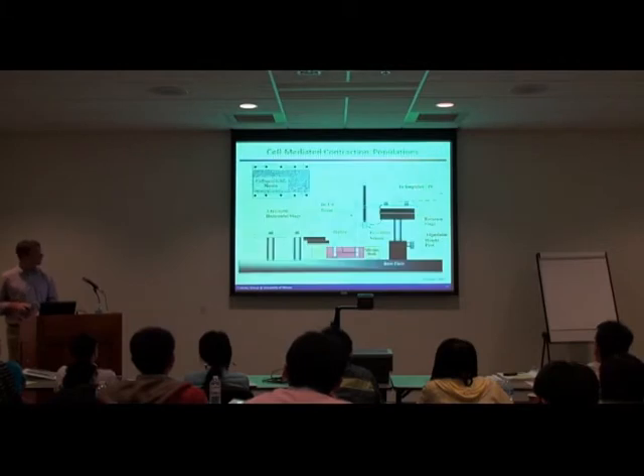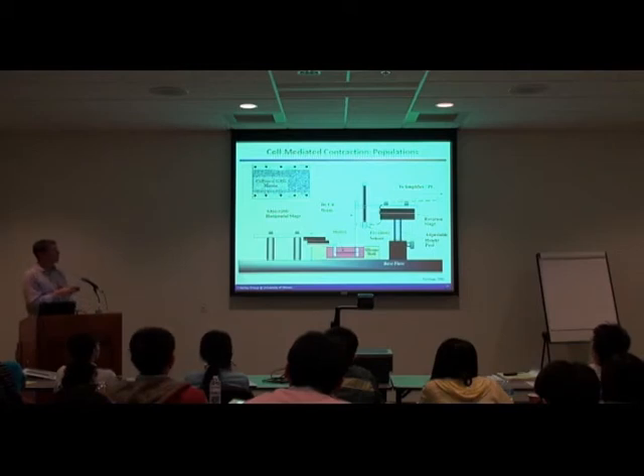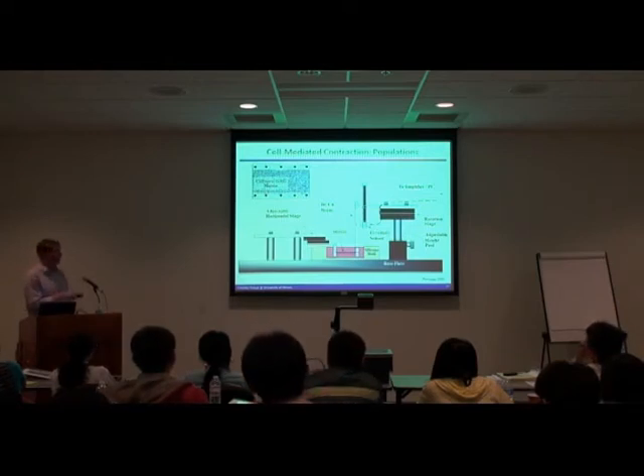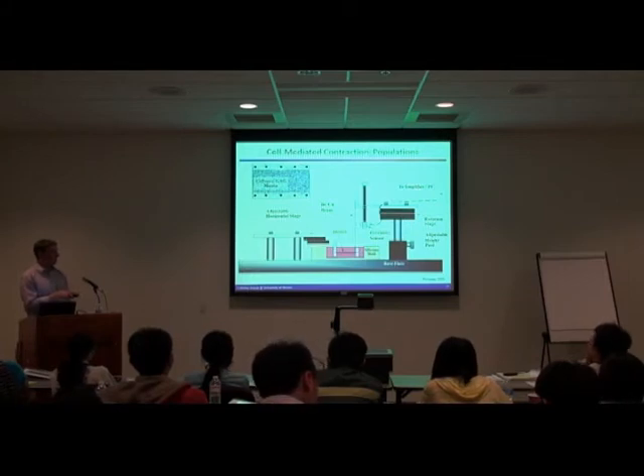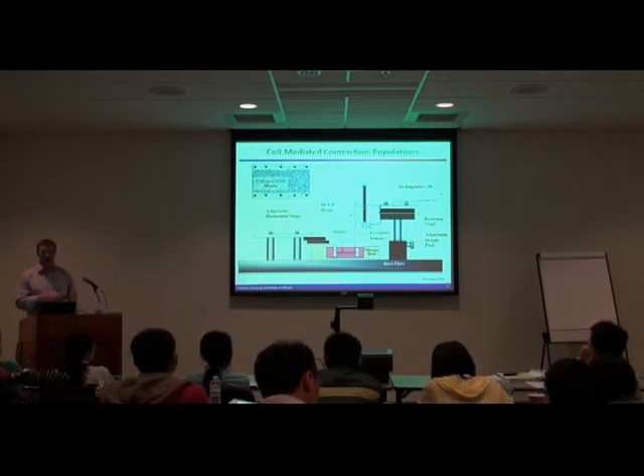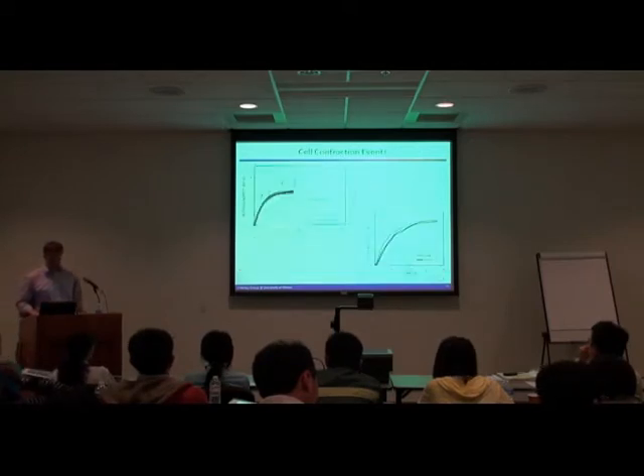And so what this allows us to do is that, well, we can make 2 different types of measurements. And so the first measurement we've been comparing it to was this sort of cell-mediated contraction of populations. And again, this idea is we take our scaffold, we seed it with 1 million or 2 million or 10 million cells, put it into some sort of measuring device. In this case, a colleague of mine, Toby Fryman, built the cell force monitor approach, which basically attached the scaffold to a very flexible beam and then measured the deformation of the beam as a way in which you can measure contraction of the scaffold.